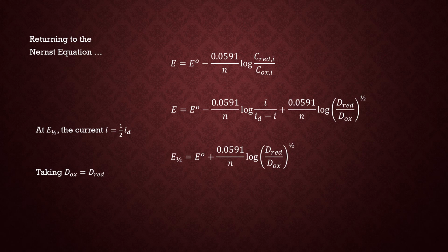The diffusion coefficients should not be significantly different for the reduced versus the oxidized form of the species. So this term should likewise go away, leaving me with the relationship that the so-called half-wave potential, the voltage indicated by the current voltage curve halfway up towards the diffusion limited current, corresponds to the standard state potential of the electroactive species in solution.